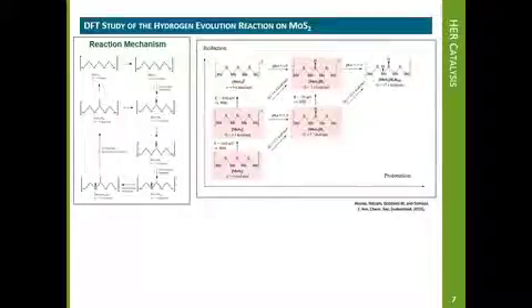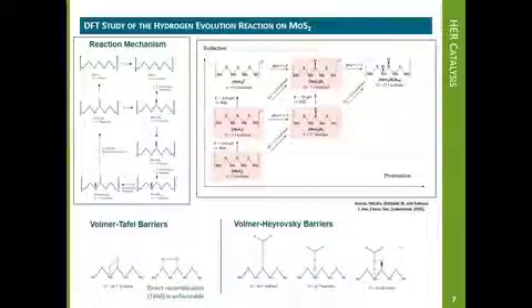To determine the reaction pathways and barriers for HER on the molybdenum edge of MoS2, DFT quantum mechanics calculations have been performed. Results show that the HER mechanism on MoS2 follows the Volmer-Heyrovsky mechanism. Highlighted in red is the pathway leading to the formation of an electron-rich molybdenum hydride that reacts with a hydronium cation. In the present case, the sulfur hydrogen species is found not to be an important intermediate since its free energy does not play a direct role in determining the effective activation barrier. Instead of equilibrium thermodynamics, kinetic barrier is proposed to be the descriptor for reactivity when designing more reactive catalysts from edge-exposed MoS2.